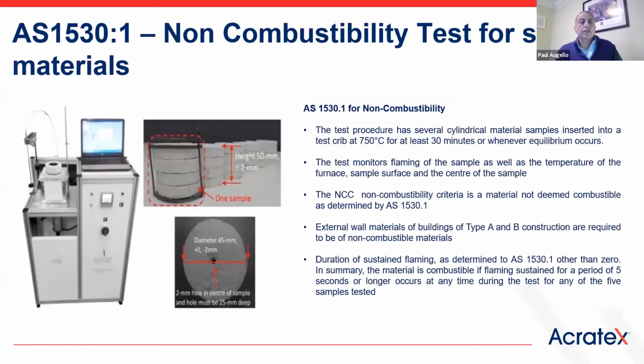And then lastly, this is the actual 1530 Part 1 test for those who may or may not be aware of it. So it's quite a severe test. You've got to basically get something to be non-combustible to pass at 750 degrees at 30 minutes.